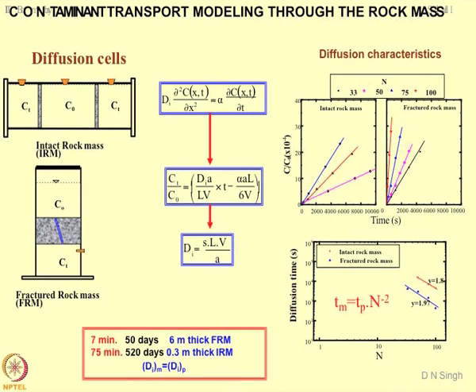So, a simple interpretation of this curve would be, if Ct by C naught is 0, what is the meaning of this? Ct by C naught will be 0 at t equal to 0, initial condition. So, this term becomes same as this term. So, if I know Di, if I know these geometrical properties, area of cross section, thickness of sample, volume, certain time, what I can get is alpha. So, alpha is nothing but sorption capacity of the material. So, by doing this simple test, you can get sorption capacity as well as the diffusion coefficient of the porous system.